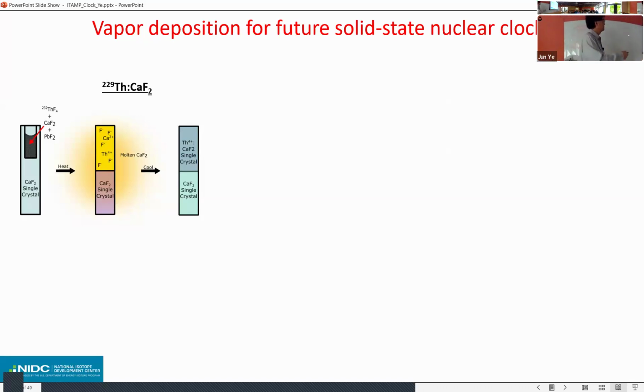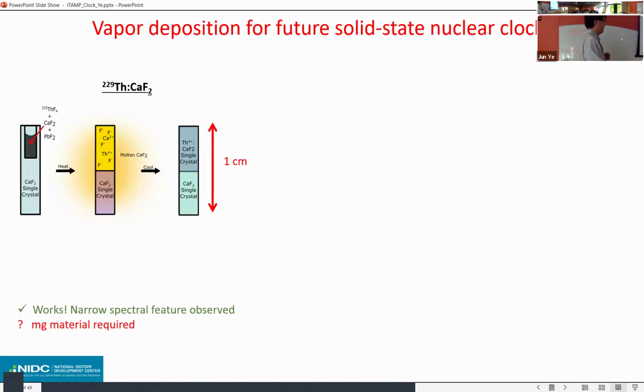that's in collaboration with Eric Hudson's group at UCLA. So this is Thorsten's crystal, how he grew this crystal, and he's going to get into the details of this. I can say this is a really beautiful system, about a few millimeters to centimeters in size, and it works. We can see narrow transitions. At the moment I showed you a 200 kilohertz line width, and I blame ourselves first. Our laser probably is not good enough, so we're going to keep working on that until we start to see few kilohertz line widths and start to see inhomogeneous splitting.